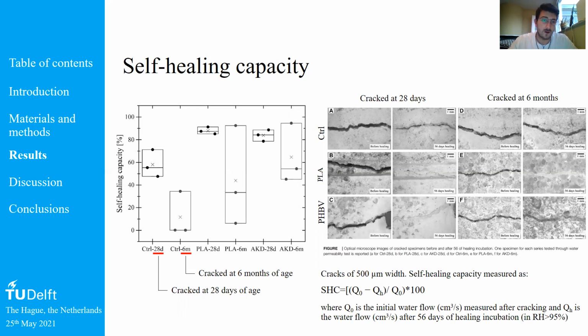On the graph on the left, we see the self-healing capacity for the samples that were cracked at 28 days. It has to be mentioned also that the cracks were around 500 micrometers in width. For the control series, those with the plain mortar, the self-healing capacity was around 60%, while for both PLA and AKD, the self-healing capacity got quite a bit higher, at around 90% for those cracked at 28 days. The bigger influence is visible for the samples that were cracked at 6 months of age, since continuous hydration of the mortar gets reduced with time. There the control series had an average self-healing capacity of around 10 to 15%, while the one of PLA was around 40%, and we got a 4 times higher self-healing capacity for AKD compared to plain mortar at 6 months.